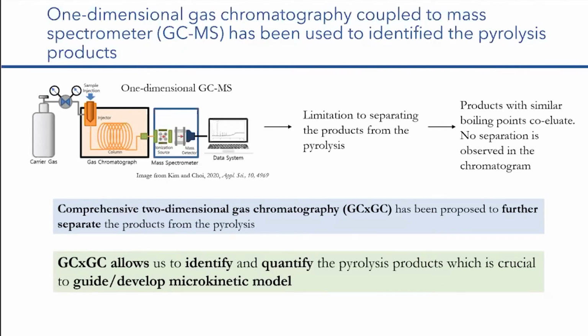Well, it is important to mention that the distribution for the pyrolysis could be very similar, and the distribution will depend on the type of polymer that we are working with. For example, for PP, we expect to see aliphatic hydrocarbons from C1 to C25, more or less. And all these hydrocarbons will have pretty similar boiling points.